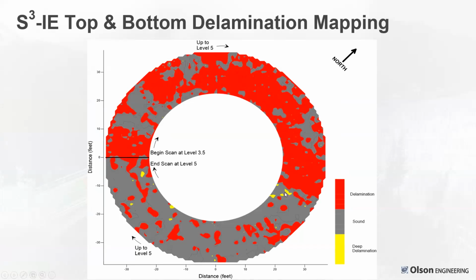What's interesting to me as well is there are certain areas that have what we call deeper delaminations. So these are delaminations at the bottom rebar mat. These are areas that might spall off and fall down onto the lower level. So these are areas that might be of particular concern. I should note that in these red areas where you have extensive surface delamination, we are not able to test down to see deeper, if there's also deeper delamination, unless we were to do testing from below looking up, which can be done, but that would have to be hand scanned.